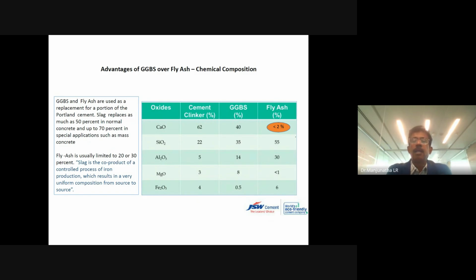Then the chemical composition. I have just given a comparison of oxides in cement clinker, GGBS, and fly ash. We have the major component oxides: calcium oxide, silica, alumina, magnesium, ferrous. We can see how comfortably the GGBS slag matches with the clinker, including the calcium oxide content. Fly ash has lesser cementitious material, less than 2%. So it will help you to a certain level. You can comfortably replace up to 25 to 30%.